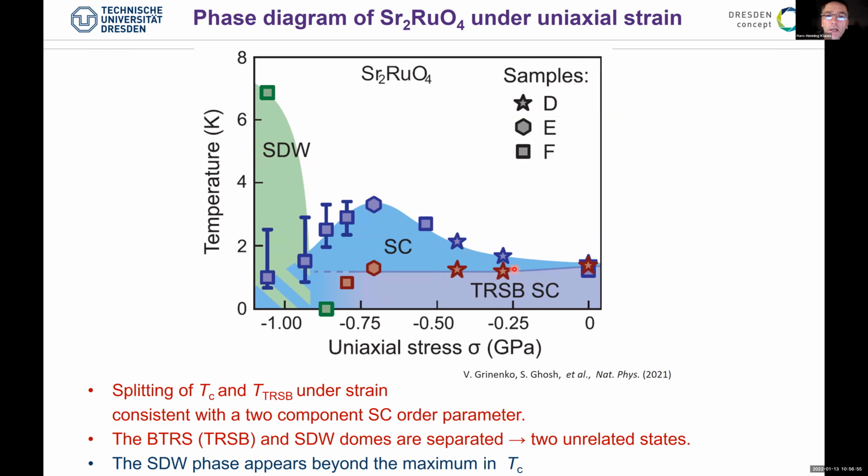So at least with hand-waving arguments, it might explain why this is more or less flat. You basically lose most of the entropy in the superconducting transition, which is perfectly fine if you have a strong splitting. If you have any model with two following order parameters, then the bigger the distance in temperature, the more entropy will be absorbed by the higher transition. But clearly in this range at low uniaxial strain, the physics is not fully clear at the present moment, I would say.